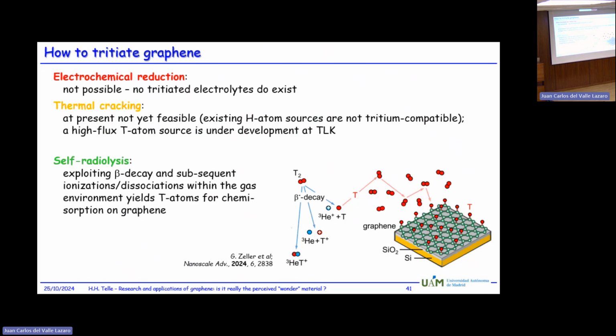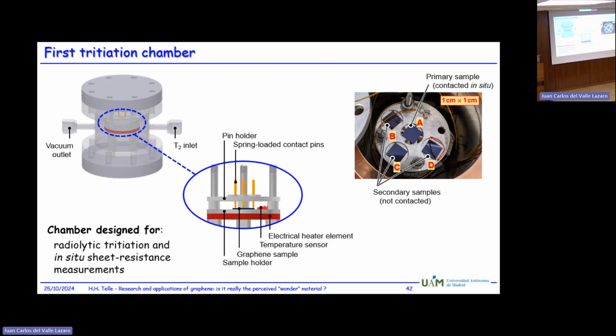So the way we actually solved the problem, we exploited the self-radiolysis of tritium, because it's radioactive, has beta decay, and in the beta decay, it actually generates from the tritium molecule helium plus tritium, helium plus tritium ion, and the daughter molecule. So basically, in this step, we have provided tritium atoms which then, because they have a large energy, are in collisions slow down and then are able to attach to the graphene surface.